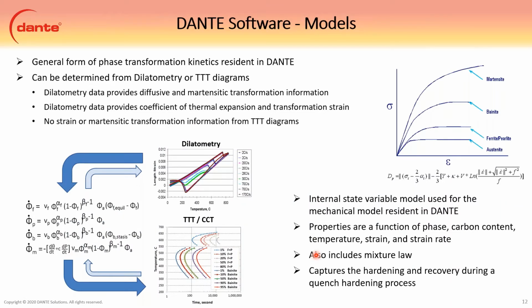All right, our models. Below on the left is our general form of our phase transformation models. For obvious reasons, I can't put the full model here, but it can be determined from dilatometry or TTT diagrams. However, we do prefer dilatometry data because it provides diffusive and martensitic phase transformation information. It provides the coefficient of thermal expansion and the transformation strains. So we get a lot of information out of one test, whereas the TTT diagrams just get us the diffusive transformation information. There's nothing about martensite except for a start and a finish temperature generally, and there's no thermal expansion or strain information at all.